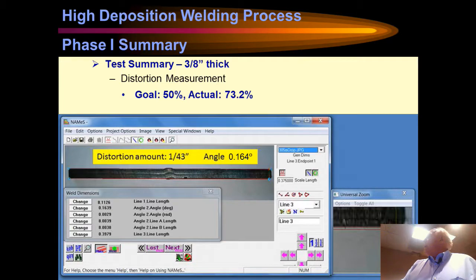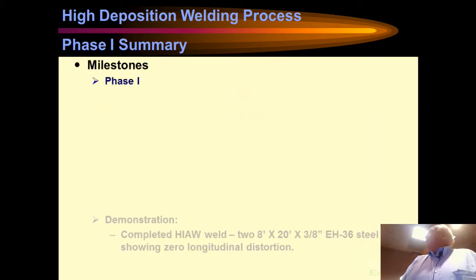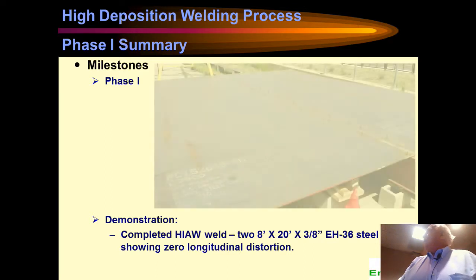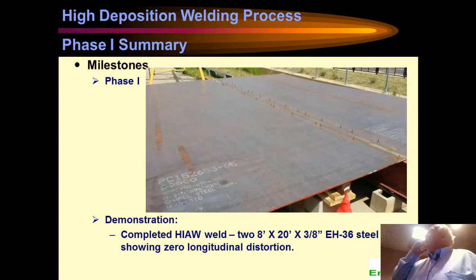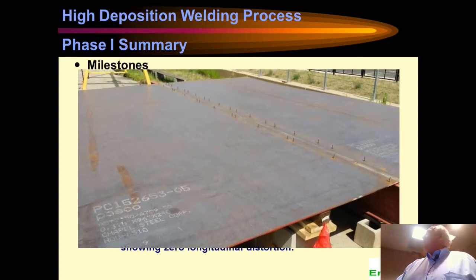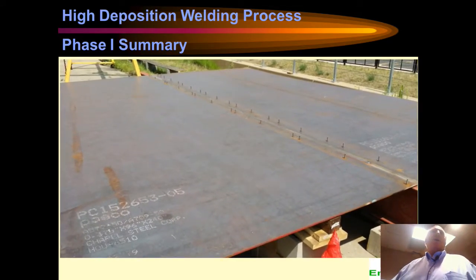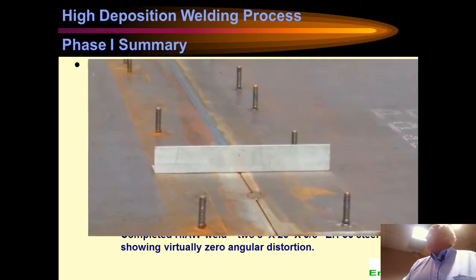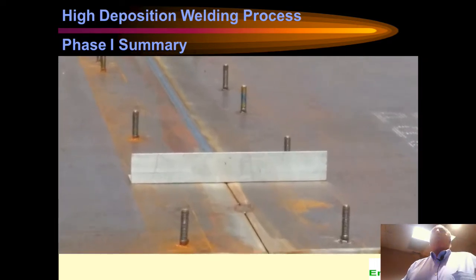Okay, so for the 3/8 we got pretty good results. We got 73.2% reduction in the distortion, and we got 88% in the 5/8 material. So the Navy was pretty happy about that. So we did a demonstration. We welded two 8-foot by 20-foot 3/8 inch thick steel plates together, and these are our plates in Lakewood if anybody wants to come and see them. They're completely flat, the whole 20 feet in the longitudinal direction, and in the transverse direction, that's a piece of angle sitting on it, and it lays perfectly flat too.